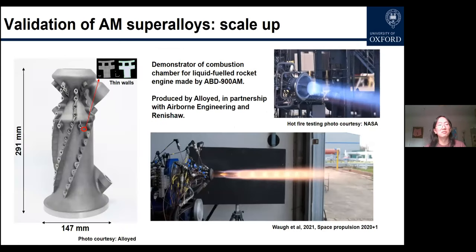Another validation we have to consider, particularly for additive manufacturing, is to scale this up. It's usually easy to print something quite small, but from experience, literature and engineering applications, these materials have too much residual stress. And when you want to build them up in size, they just become undoable. They start to crack.